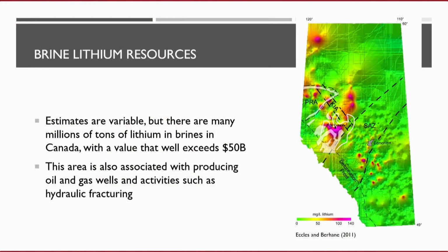So we're looking at brines in deep sedimentary basins. These are down several kilometers in most cases. And these brines that we have, I'm showing the example since we're here in Alberta, and I'm up at the University of Alberta, the Western Canadian Sedimentary Basin. But you can see that in Alberta, we have concentrations that vary from no lithium up to over 100 parts per million lithium. And this would be consistent across British Columbia and also into Saskatchewan, where the concentrations are a little bit higher, in North America in general.